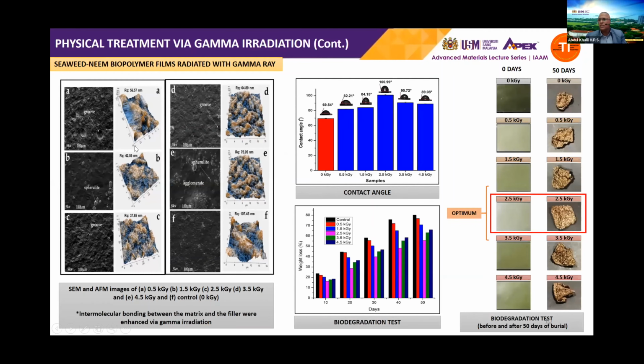In this slide, the result of the finding can also be observed. First, through the SEM and AFM images of seaweed neem leaf biopolymers, it showed that the surface roughness reduces as the dose of gamma ray increases. This finding is also associated with a cross-linking process between seaweed and neem induced by gamma irradiation. The contact angle of the biopolymer film also increases upon increasing irradiation up to 2.5 kilogray. This is due to the reduction of hydroxyl groups in the seaweed neem biofilm, which lowers the surface energy and makes the film more hydrophobic.